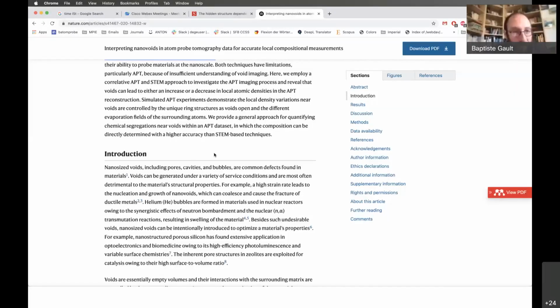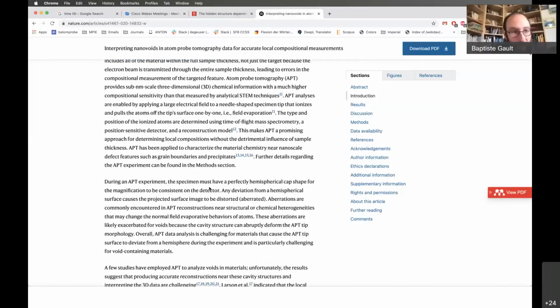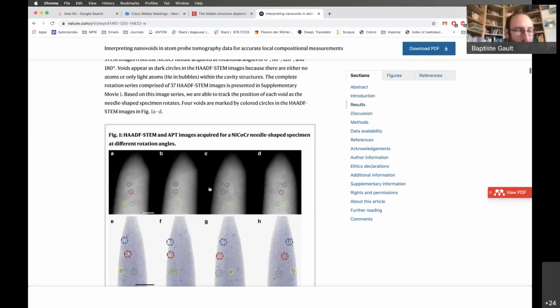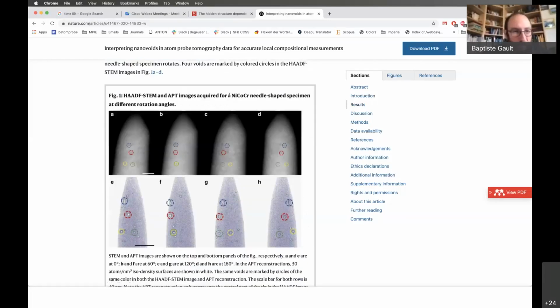So this is a collaboration with friends from Oak Ridge National Lab. They made these needles, and these are irradiated samples, nickel chrome, cobalt chrome, I think 33%, one of these medium entropy type alloys. But anyway, here it's been irradiated and it's full of small voids. So they can see them from the STEM.